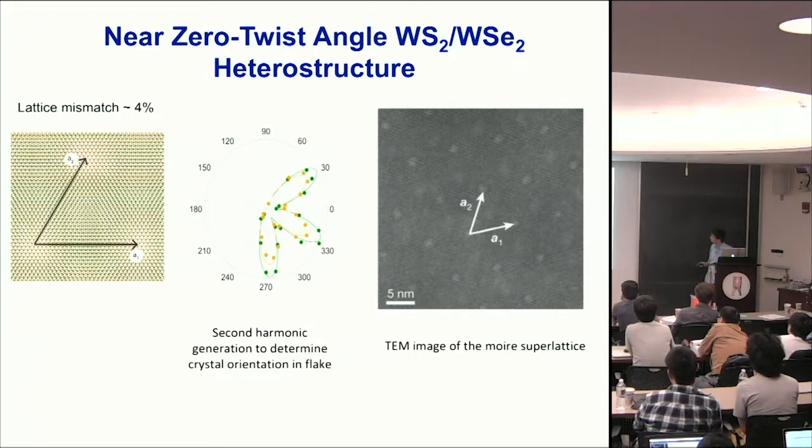We also noticed that unlike this Moire superlattice, which exists but is more spread out, this Moire superlattice looks like fairly concentrated points. That's an indication there's fairly strong lattice reconstruction in this situation when the two layers interact with each other. So that's a good thing that tells us they are indeed interacting fairly strongly and can have large effect.